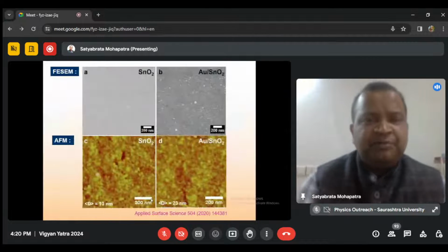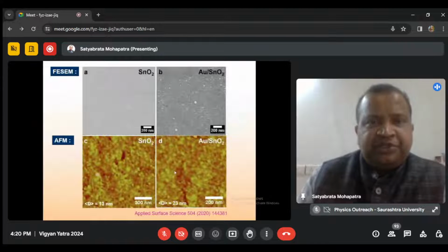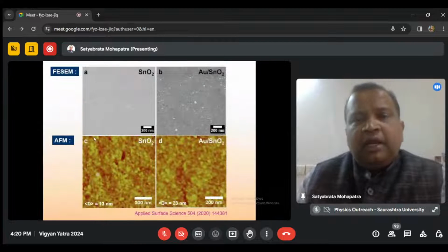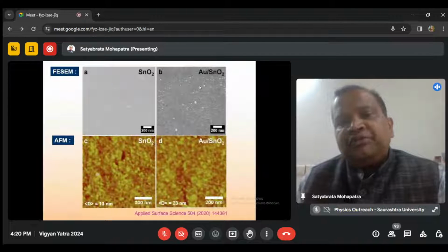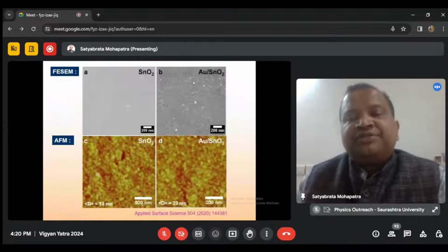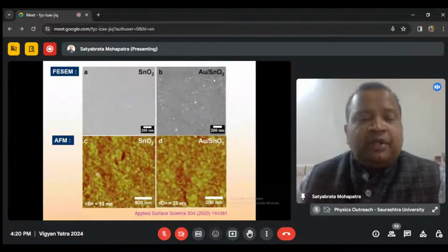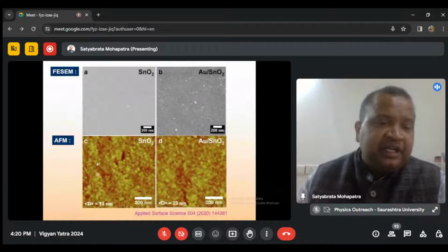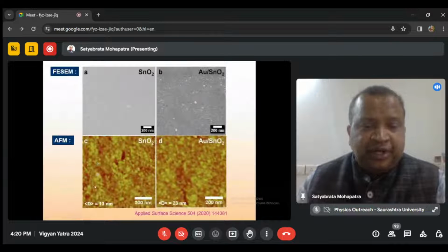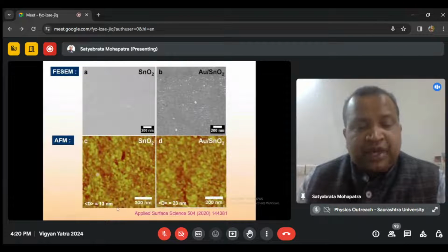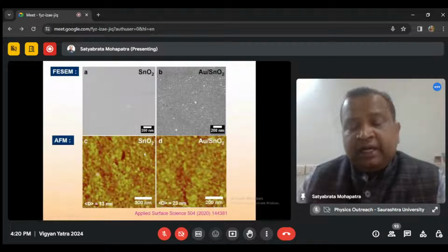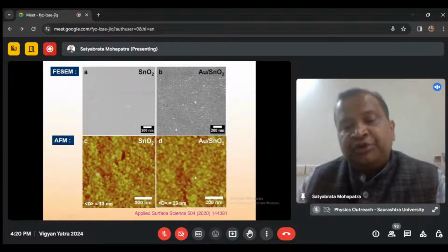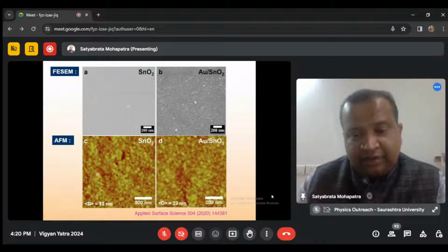Now, FESEM shows a pristine tin oxide film, and on gold coating you can see nanoparticles of gold decorating the tin oxide film surface, which is again clearly evident in the AFM results in C and D, where the average nanoparticle size is 13 nanometer in the case of pure tin oxide, and increases to 23 nanometer in the case of gold on tin oxide.